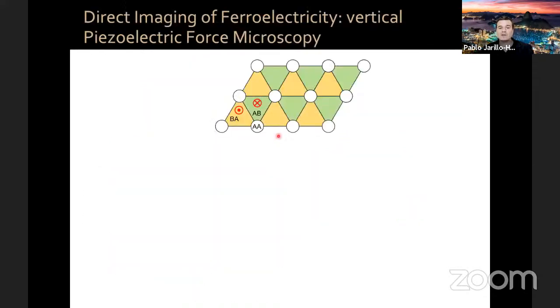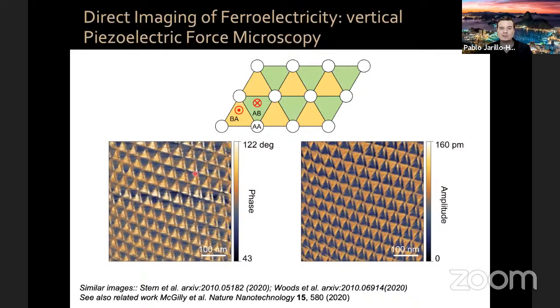In fact, very recently we have been able to directly image the ferroelectricity using vertical piezoelectric force microscopy. This is the phase image. This is the amplitude image. This is showing directly the electric dipole moment of these AB and BA domains in a twisted bilayer boron nitride device. This confirms 100% our ferroelectric switching behavior that we presented before. Similar ferroelectricity through vertical piezoelectric force microscopy was shown in these other two papers.